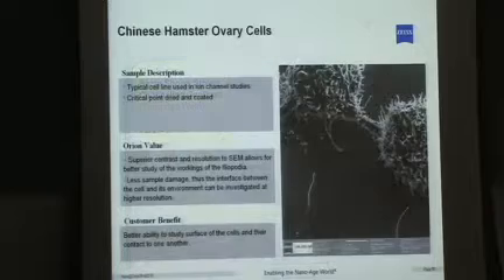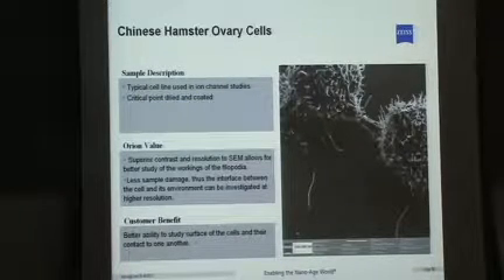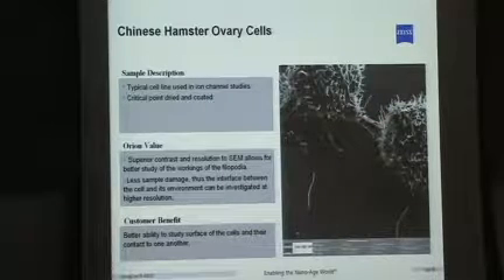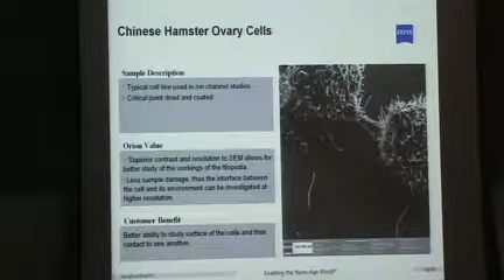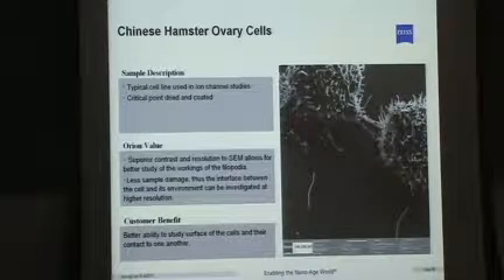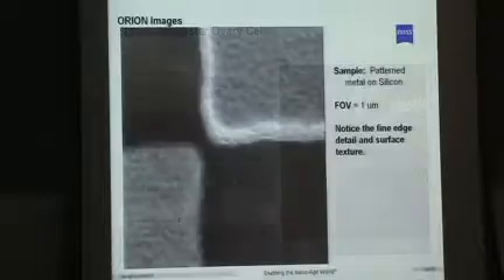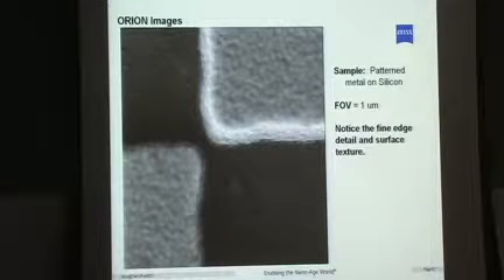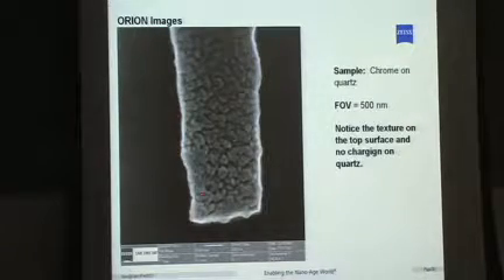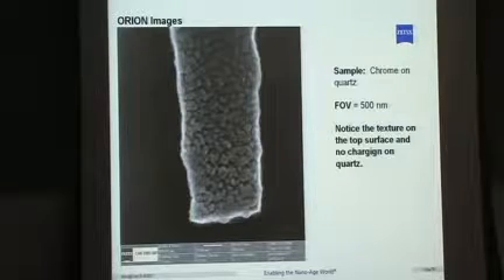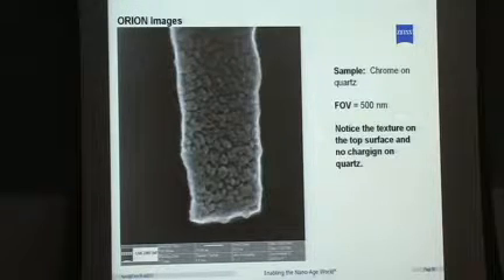These are some dried and coated, I believe, hamster ovary cells that came from our one customer's site that produced a really interesting contrast. And this is gold that's been patterned on top of silicon. This is a 1 micron field of view, so you can see there's really some very fine texture there. This is a 500 nanometer field of view. This is chrome on quartz, a typical semiconductor challenge. Again, not a charging problem for us, even at this very high magnification. These grains are on the order of 10 nanometers.